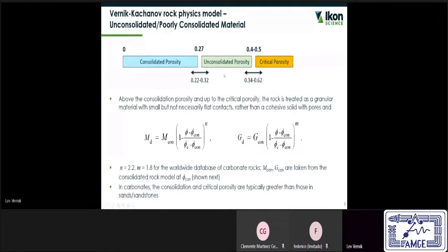But in order to handle this tricky transition zone, we introduce these two functions here. So the significant element of each of these functions, this is a P-wave modulus for dry rock, and this is a shear wave modulus, of course, is this dependence on the modulus of the consolidated rock at the porosity, which we call the consolidation porosity. So that's a transition period between the consolidated and poorly consolidated domains. So this consolidation porosity, in addition to critical porosity, is also dependent, just like critical porosity, on grain sorting characteristics of any specific rock. And of course, the N and M exponents are parameters that can be easily calibrated. They are pretty tightly distributed around P.